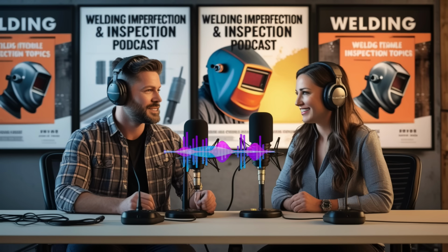Got it. So what are some of the common reasons for lack of sidewall fusion? Why wouldn't it stick to the sides? Often it comes down to insufficient heat input. Basically, the weld pool isn't hot or fluid enough to properly melt the adjacent sidewall material and fuse with it. Not hot enough. Right. This can be caused by using too low a welding current or voltage for the material thickness and joint type, or by welding too quickly, not allowing enough time for the heat to transfer. Okay.